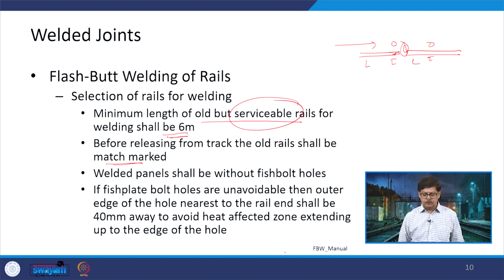The welded panel shall be without the fish bolt holes, the same condition as we discussed in the case of AT weld. Now, if fish plate bolt holes are unavoidable, then outer edge of the hole nearest to the rail end shall be 40 mm away to avoid heat affected zone extending up to the edge of the hole. So, if we have a rail and this bolt hole cannot be avoided, you cannot crop it. So, in the case of AT weld, we said that you should crop it and then use it for the weld. Here what we are saying, if it cannot be removed, then this bolt hole which is nearer to the end, this shall be